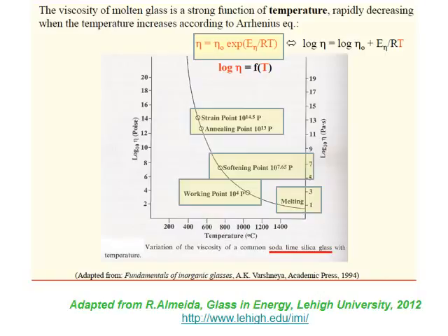We have already commented on the need of annealing in order to release stress. This stress release occurs in some minutes if annealing is performed at Tg, and in some hours if performed at the strain point.